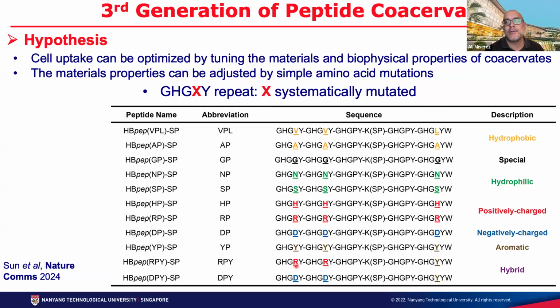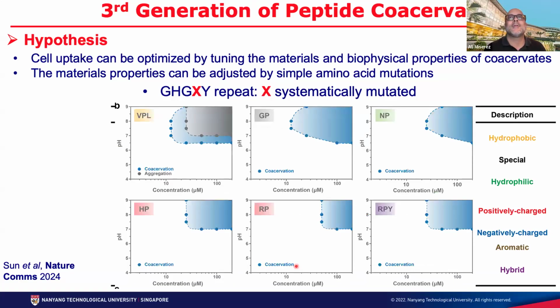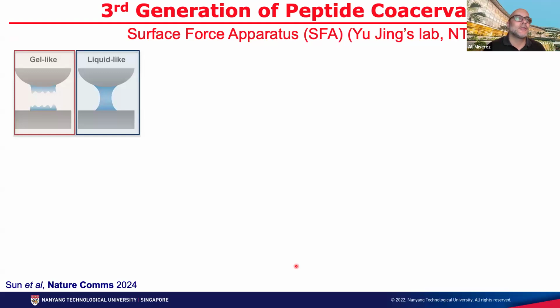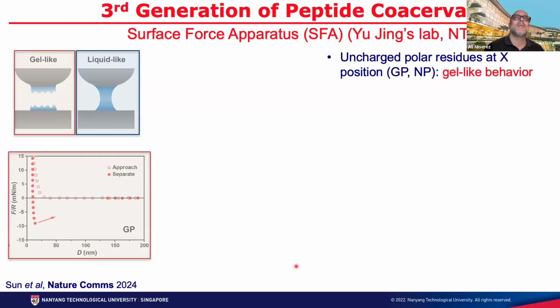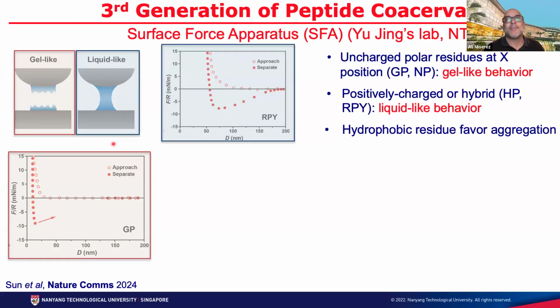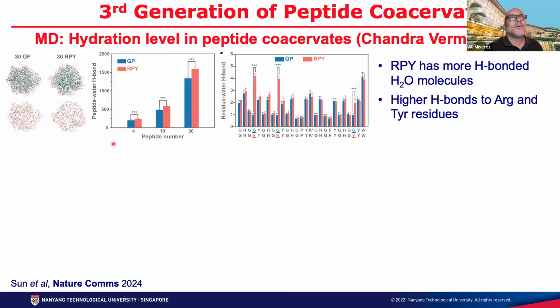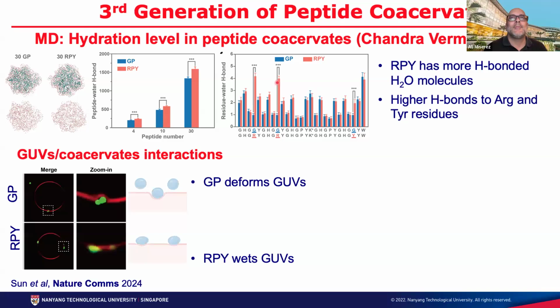And what we found is that this changed completely the mechanical or material properties of those droplets. Some of them become more liquid-like, and some are more gel-like, by just a few amino acid mutations. Depending on the amino acid residues that we add inside our peptide, we can make those droplets more gel-like, a bit stiffer, or liquid-like, where they really maintain their liquid-like behavior. And the reason I'm telling you this is that, based on molecular dynamics simulations that we do with our colleague here in Singapore, what we found is that more liquid-like droplets have more molecular hydration. So you have hydrogen-bonded molecules in specific regions of the peptide.